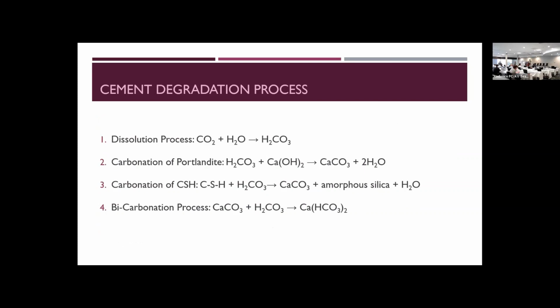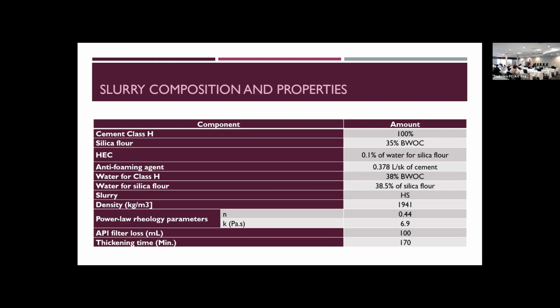Now, degradation is a big issue, and we have known for a long time that cement degradation happens in the presence of CO2, although there is a lot of discussion right now about what the right model for degradation is. But what is important here is that in the cement, we have the carbonation of Portlandite and the carbonation of the CSH phase. These two are very important for the degradation process that I will show you in what comes.